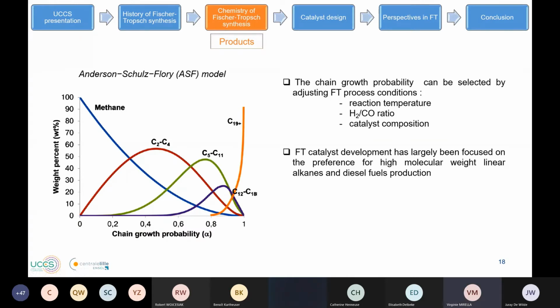So, different factors. Here we have the Anderson-Schulz-Flory model. On this model, we can see that we have different products that can be produced from Fischer-Tropsch synthesis: methane, olefins, C5 to C11, C12 to C18, and C19+. And the chain growth probability can depend on the reaction temperature, the hydrogen to CO ratio, and the catalyst composition.